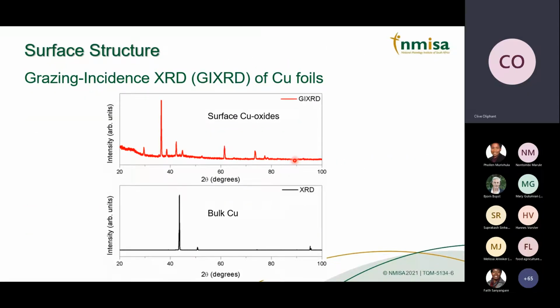Here is also the surface structure of a copper foil that is used to manufacture graphene. Graphene is one of those 2D materials that has been identified to be industrially relevant, and in South Africa there is some activity in it. So NMISA is already laying the framework, or laying the foundation, for it. So this is a grazing incidence X-ray diffraction pattern of copper foils. If you do normal XRD, you will just see copper. However, because we want to view the surface, we use grazing incidence XRD, and now we can see the copper oxides.